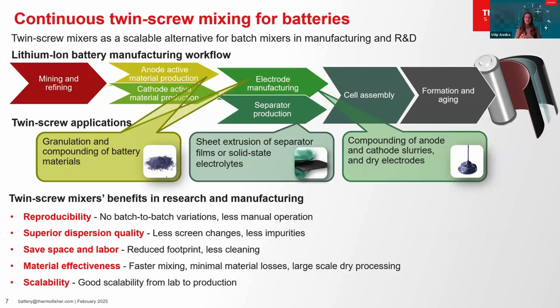For example, for compounding electrode active materials, twin screw mixers can be used, for example, for granulating silicon anode materials and fully solvent-free cathode materials. They are also used in the process of dry electrodes. Separator film production: conventionally, separator films are produced by extrusion, and it's a well-developed process. But for novel battery concepts such as solid-state batteries and gel polymer separators, lab-scale twin screw extruders are particularly beneficial. For electrode manufacturing, twin screw mixers enable the continuous mixing of cathode or anode slurries, and this offers a beneficial alternative to batch mode mixing, typically done with planetary mixers.